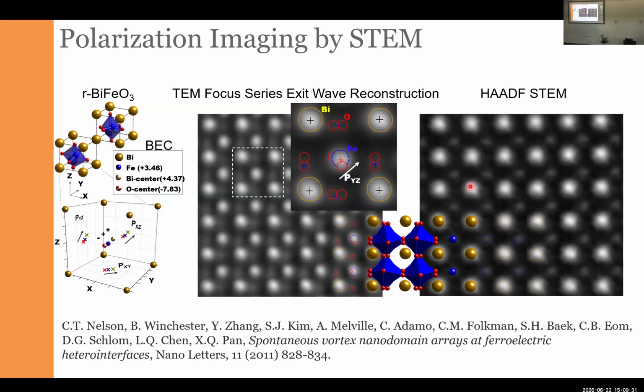As simple as that. And then for many things like order parameter fields, for example, for polarization, you can simply find the high intensity columns, find the geometric center, kind of the cross-section of the diagonals, and then you can see to which extent the central atom is off from the position of this geometric center. So the fact that this was possible was absolutely astounding, because typically people think about polarization mapping having a big crystal, doing the X-ray measurements, and so on, and all of a sudden you can just physically measure the displacement of the atom compared to the high symmetry position.